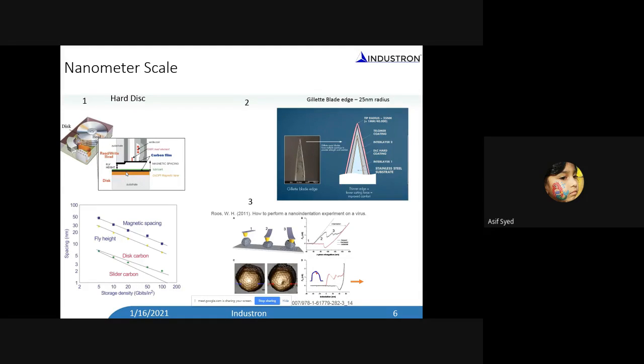So 20 years ago, it was about 30 nanometers. In today's time, those gaps are reducing to about a few nanometers. And in that process, you also have to reduce the size of these coatings, the DLC coatings. You can't have thicker coatings. The coating has to be within a nanometer or less.